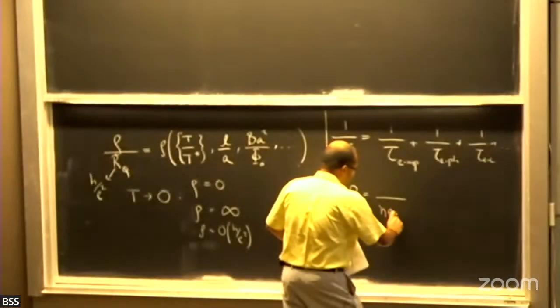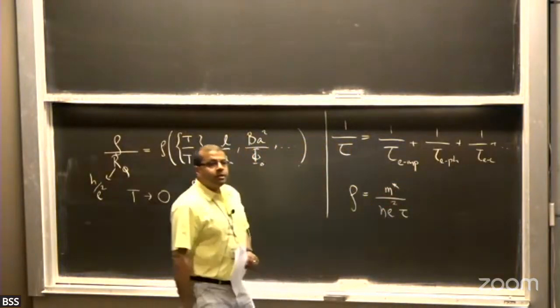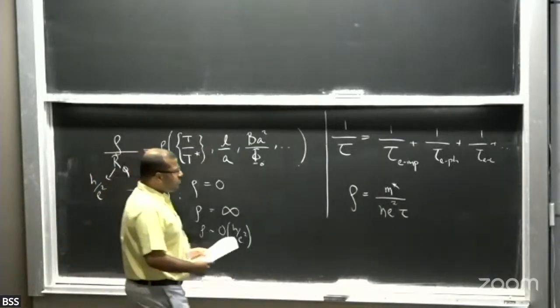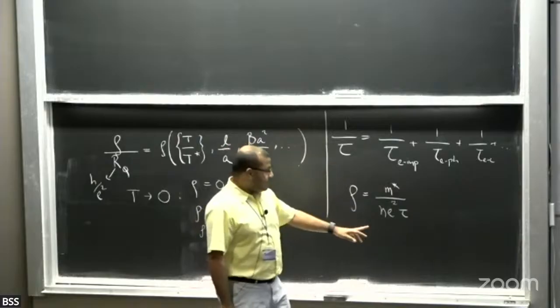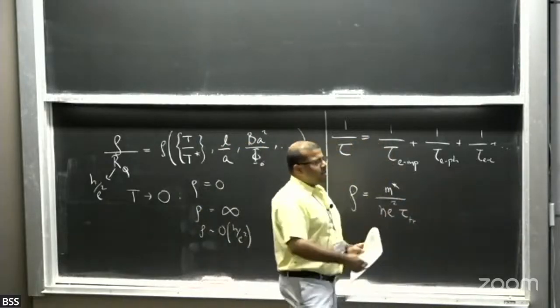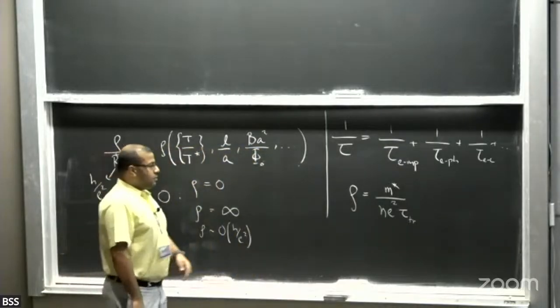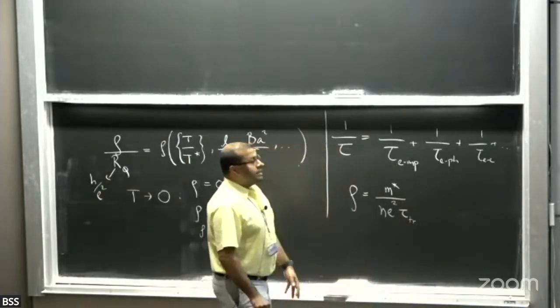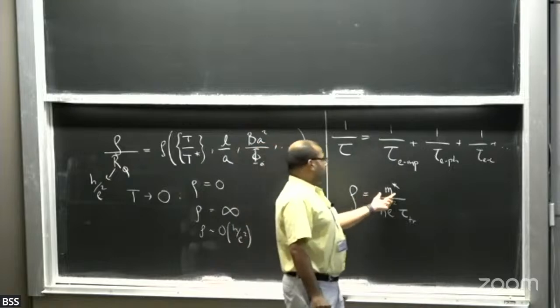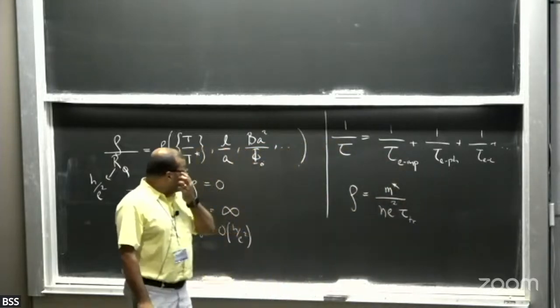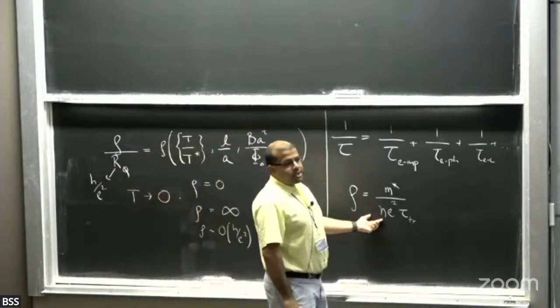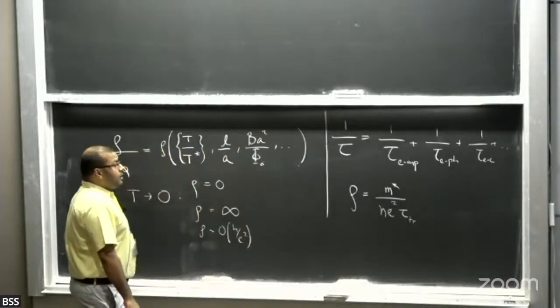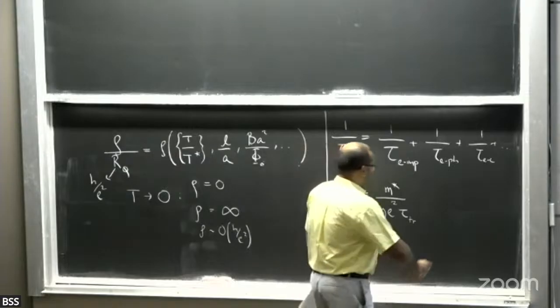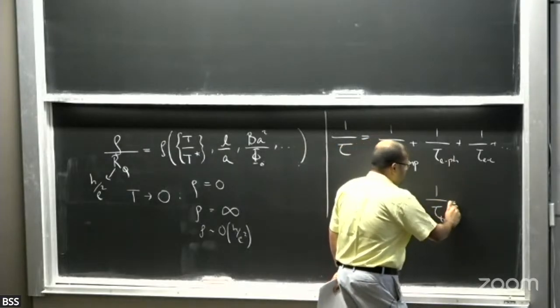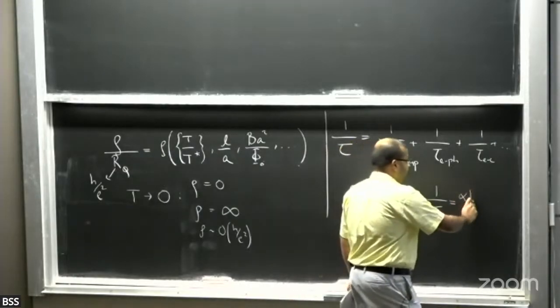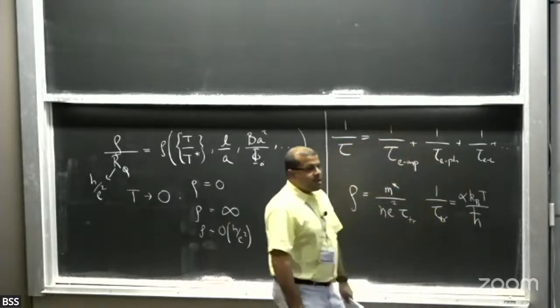And this is the DC limit of the Drude resistivity. N is the carrier density, m star is some effective mass, E is the charge, and tau is what I denote there as the transport scattering time. Okay, so 1 over tau transport is the scattering rate. Okay, so now in the experiment, you try to get m star from some independent measurement, maybe quantum oscillation, specific heat. You try to get the carrier concentration from Hall or again, quantum oscillations. And then, in a regime where the resistivity looks T-linear, you assume that this has a form like that.